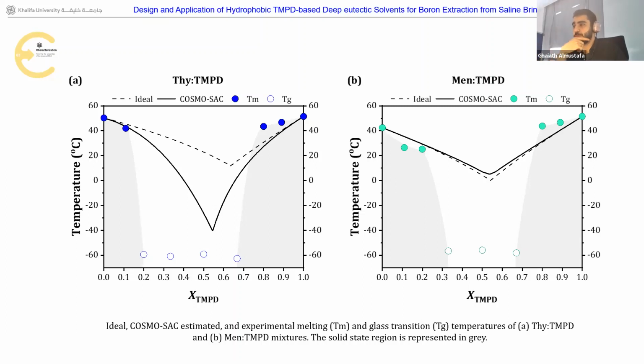This is the glass transition point. And I have plotted in the dashed line here the ideal behavior. This is how it should ideally behave. And this feeds into that definition that I showed you earlier, that the deep eutectic solvent is defined by how much depressed we are from the ideal behavior. And this is granted for both systems.